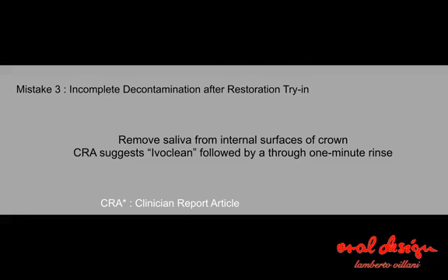I also suggest sandblasting the internal crown, inside the crown. 1.5 bar is enough, that's the pressure, and you clean with 50 micron sand.